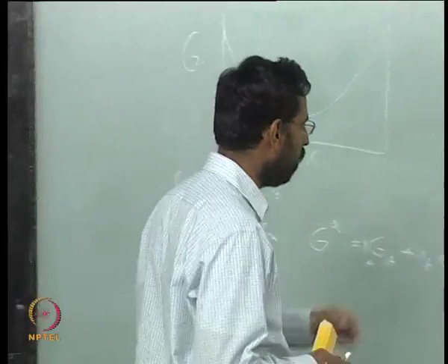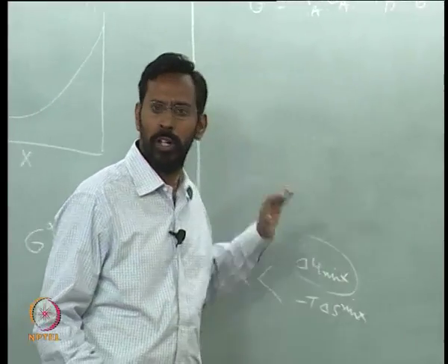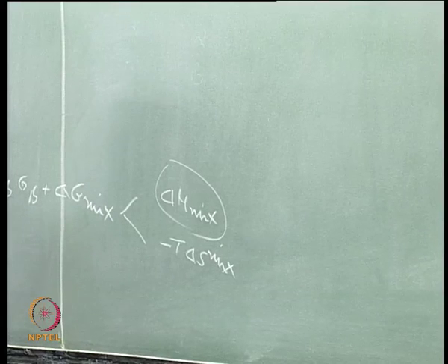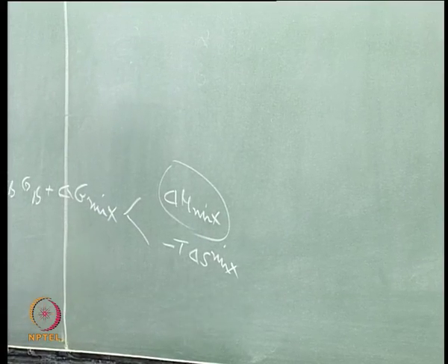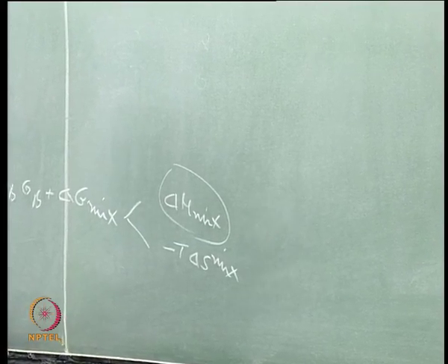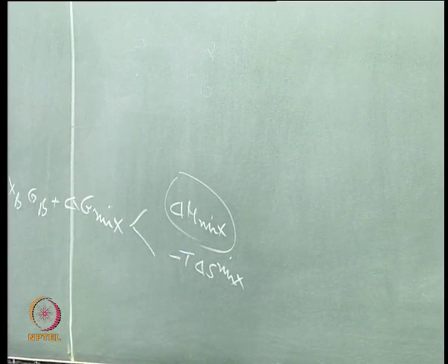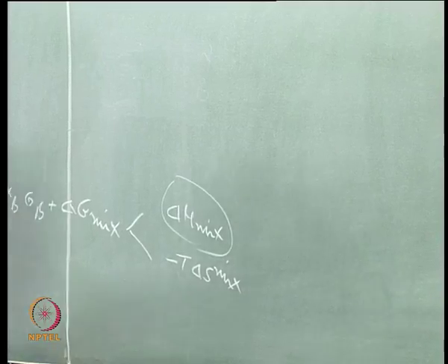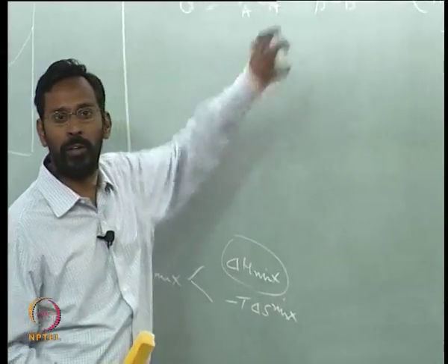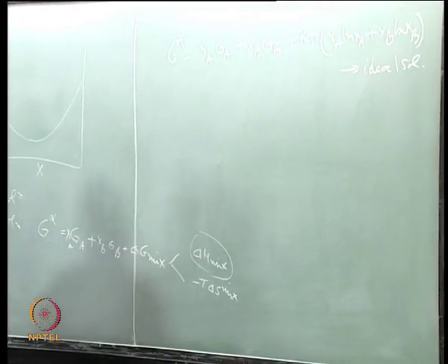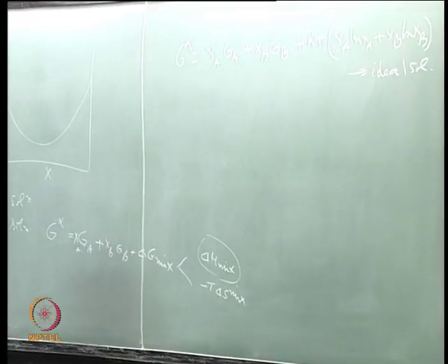There are a large number of people who have been measuring this delta H mixing, and from that we can come to know whether they are forming intermetallic compounds or whether there is a repulsion between them, because of which delta H is positive, and then you try to fit the measurements to the model and say yes, my model of regular solution or subregular solution is working.